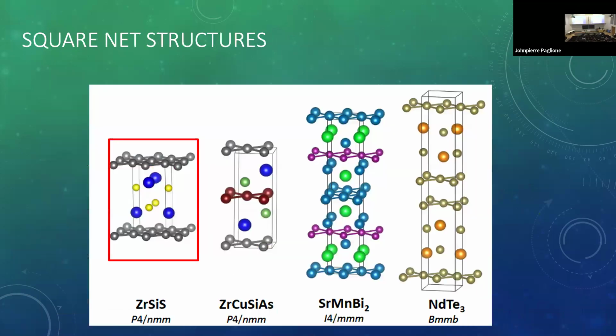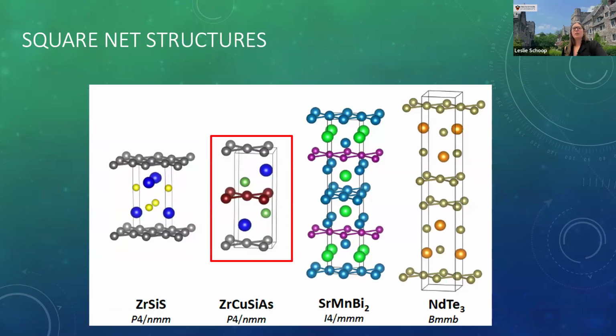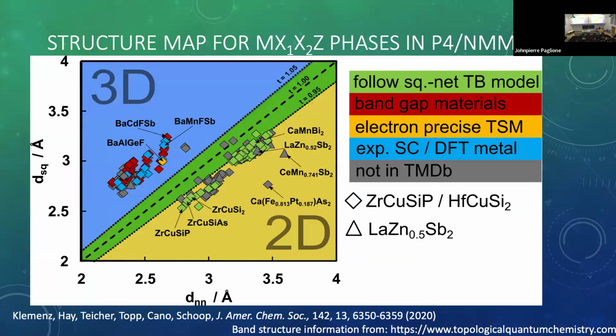So we can see if it works with another crystal structure also. So we do it with this crystal structure. Here's the same kind of plot. This time I color-coded it a little bit differently, based on the band structure that they show based on simple DFT. So we just look at the databases which use PBE-based DFT. And so whenever we colored it in green, it has a band structure which follows this tight binding square net model based on DFT. So we can expect these Dirac cones to be there. And you see the green dots are all in the yellow area of the plot as predicted.